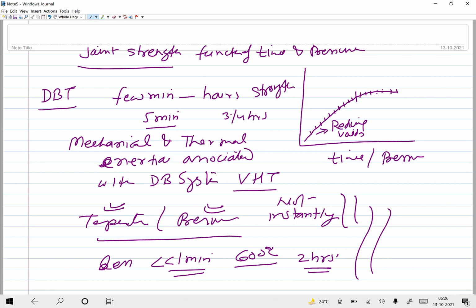Okay, so apart from the diffusion bonding temperature, which significantly affects the diffusion bonding coefficient, the average diffusion length x is affected by the diffusion bonding time and the temperature. In order to develop a sound and reasonably good metallurgical bonding and the desired strength, it is important that sufficient diffusion bonding time is allowed. But in diffusion bonding it takes very long to develop the metallurgical bond.